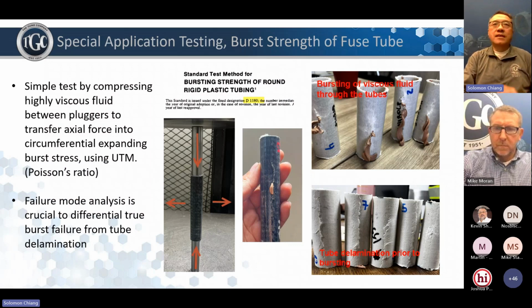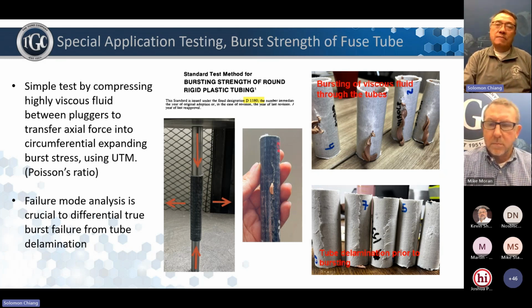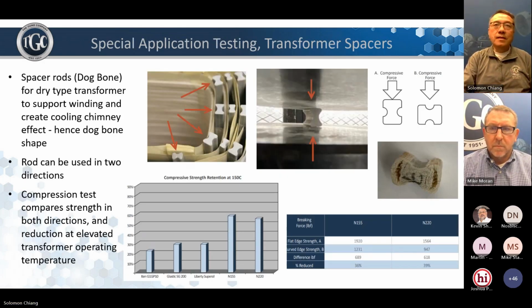And this test also detects delamination. So if the filament wound tube or common wound tube used in the fuse strip holder was not made properly, it will fail in delamination before actual burst failure. So that's an example of the failure mode being useful. Won't go into this one too much. This is the dog bone.